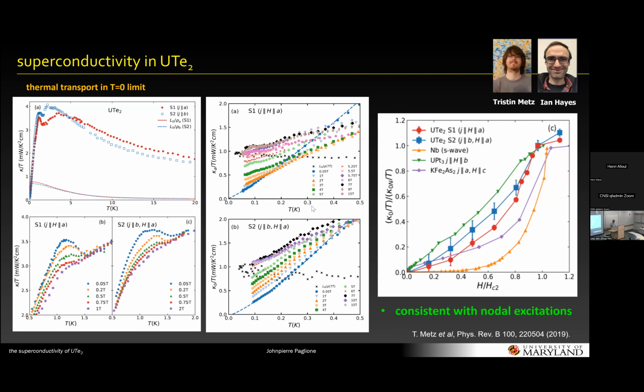Okay, thermal transport, the studies we did early on, were also consistent with a nodal order parameter symmetry in that the residual fermionic thermal conductivity at low temperatures actually goes to 0, but rises very rapidly with magnetic field and with temperature. At least consistent experimentally with several other nodal superconductors, and we've been studying that since then.